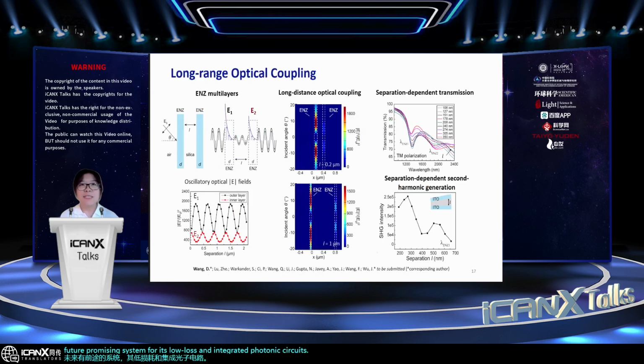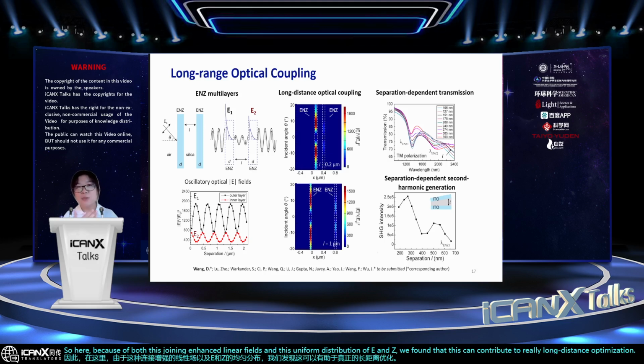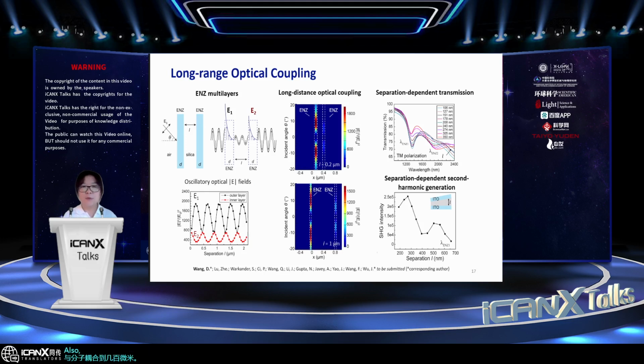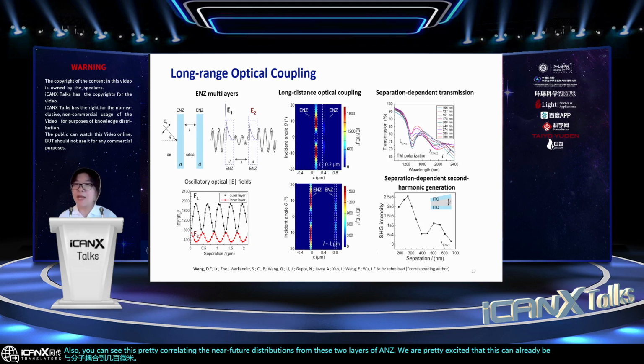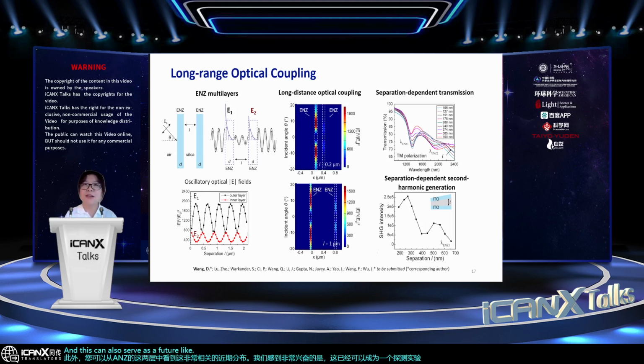Another thing we found interesting is these multiple layers of ENZ materials. Here, because of both the strongly enhanced near fields and the uniform phase distribution of ENZ, we found that this can contribute to really long distance optical coupling, up to hundreds of microns from simulations. Also, you can see this pretty correlated near field distribution from these two layers of ENZ. We're pretty excited that this can already be probed in experiment in both linear and nonlinear optics. And this can also serve as a future interconnect, a long range optical coupling between different quantum emitters.